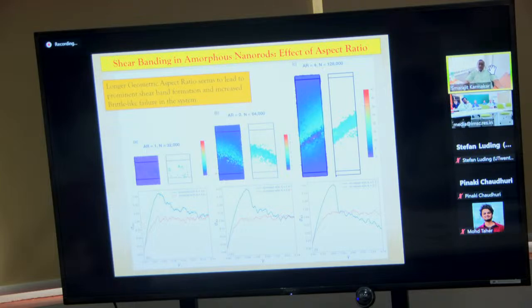These are the pillars which are annealed using active particles, or you can also anneal them by oscillatory shear. I did not talk about it in detail. If you take this system with aspect ratio 1, so basically a cubic pillar, and you pull it, the shear bands are not very clean. But if you take a pillar with an aspect ratio of 2, height versus the base, you get a shear band which is much cleaner than the cubic one. And if you take an aspect ratio close to 4, you get a very clean shear band.